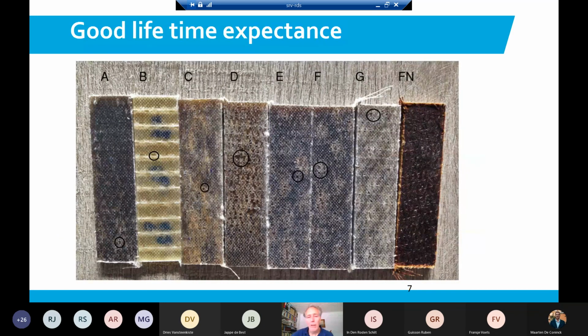So we made different types of samples together with 100% bio-based resin. The sample up on the right side, that's a grass fiber with a natural-based resin, a furan-based resin, so that's 100% bio-based. And what we did, we put these samples in an accelerated weathering tester, so with high moisture and very high ultraviolet light coming on the samples. We measured the mechanical properties in the beginning, and then after 1,000 hours in the accelerated weathering tester to see if mechanical properties remain the same or that they go down rapidly.